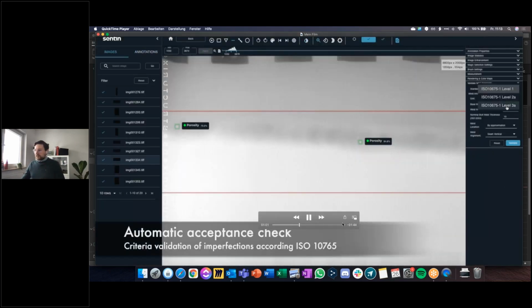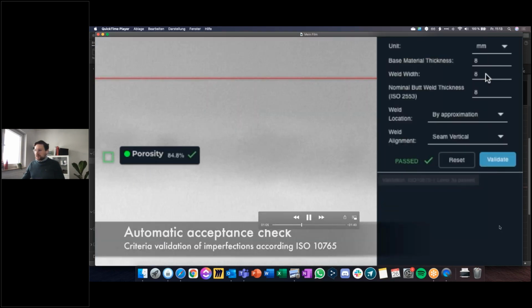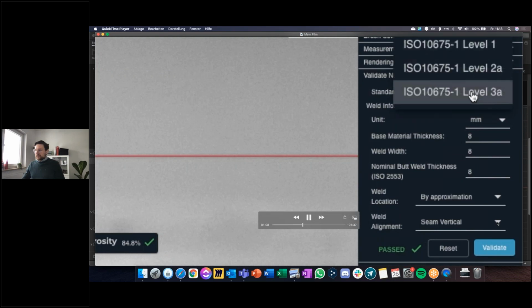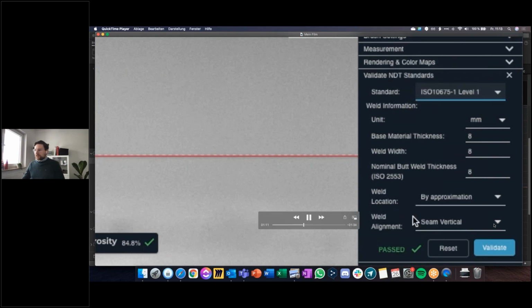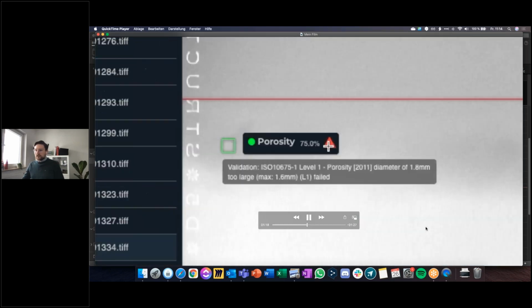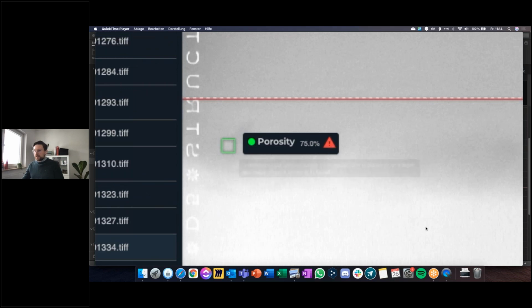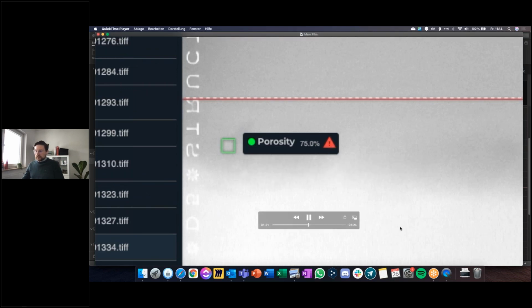And then once again, this is the line profiling, where you can see the gray value distribution, and this is where we can validate, or shown how to validate, the found flaws according to NDT standards. So you can see that we changed the standard to level 1, and before that we passed the test. Now we reset it and revalidate it, and now we failed, and now we even get the indication why it failed, why the weld seam is not acceptable, and we get an indication here.